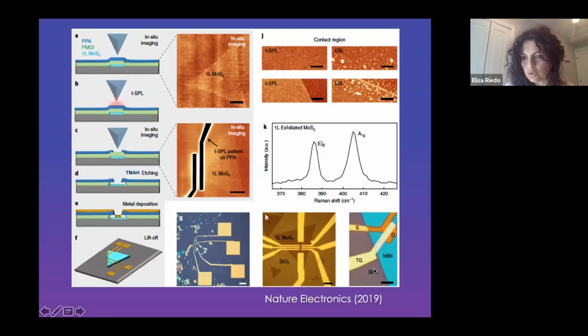You can create also top-gated field effect transistors, where for the top gate you can use the Nanofrazor beautifully to really image where the two electrodes, source and drain, are, so that you can visually see where your top gate, in the middle, can actually be fabricated. So you don't need markers at all. That's a big advantage compared to e-beam lithography. Another advantage over EBL is the cleanness of the surface, as you can see here.